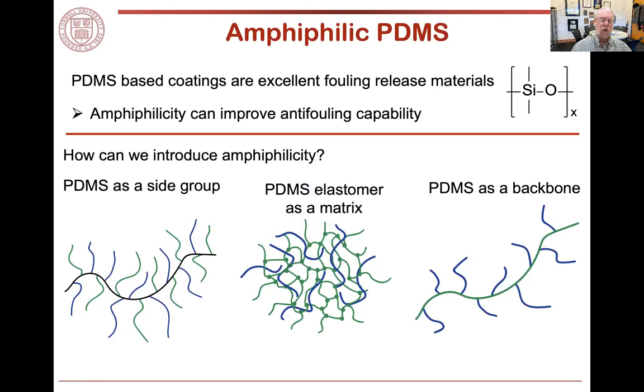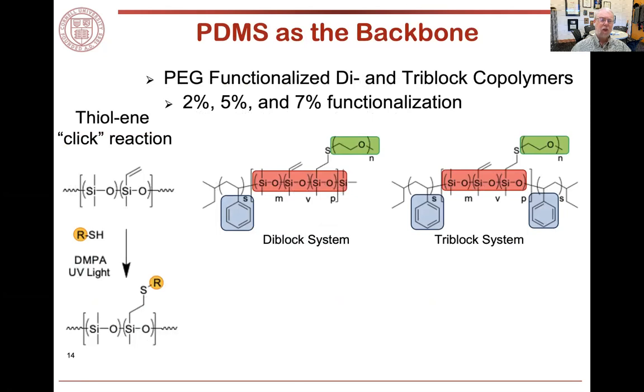We have carried out an extensive range of studies, and over time we focused on silicone types of materials. There's a wide variety of means and architectures for producing an amphiphilic polymer with silicones. We've identified structures with PDMS as the backbone, and generally incorporation of polar groups as the side chains, as a good means for introducing this amphiphilicity. If we look at a block copolymer with PDMS, we use thiol-ene click chemistry to modify the PDMS backbone with, in this case, a PEG unit. We can use anionic polymerization to create either a diblock or a triblock material, and then make this amphiphilic PDMS block.